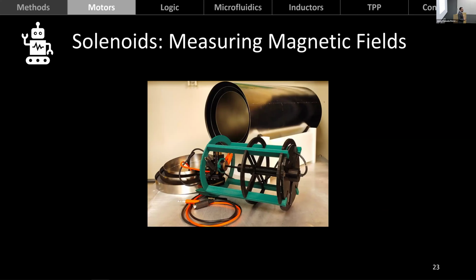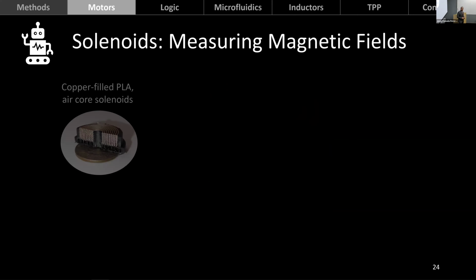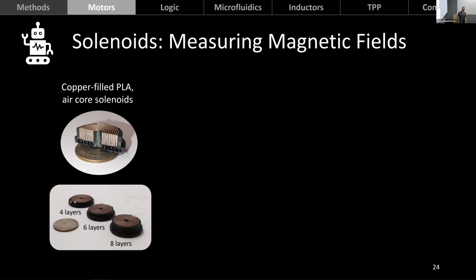And so the way we characterize these solenoids was by measuring the magnetic fields that they generate. This is the experimental setup, which has a magnetic shield and a 3D printed support structure that holds the probe and the sample in place. Now, we started with the first iteration of the solenoids that we made, which have the copper filled PLA filament as conductive material and no core. And we were able to print them with multiple numbers of layers.